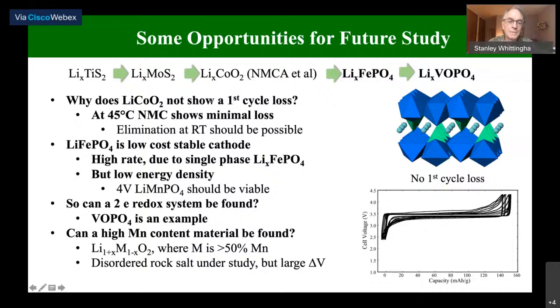I've discussed the lithium cobalt oxide. Lithium iron phosphate, I mentioned, is a low-cost, stable cathode used extensively in China. And it's extremely high rate when we make it single phase. We do this by doping it with a bit of vanadium or magnesium, but it has a much lower energy density than NMC. My colleagues here, Sherju Preti and others, are looking at the manganese equivalent that has almost 4 volts. The other issue or good point about this lithium iron phosphate is a tunnel structure.